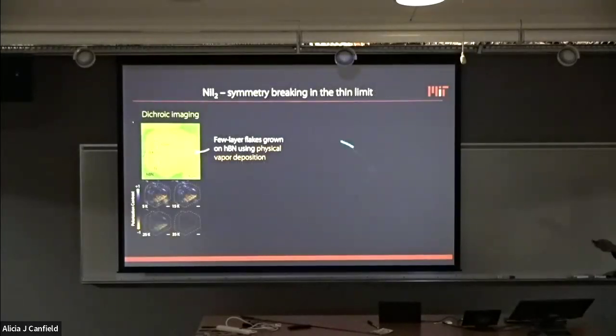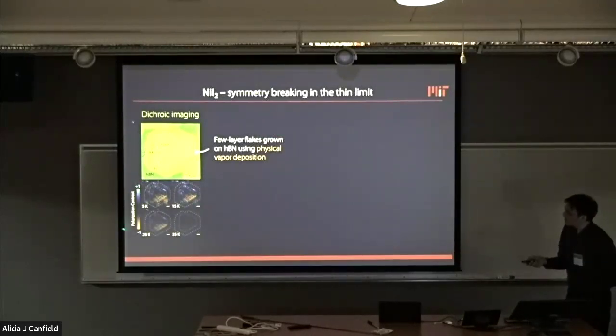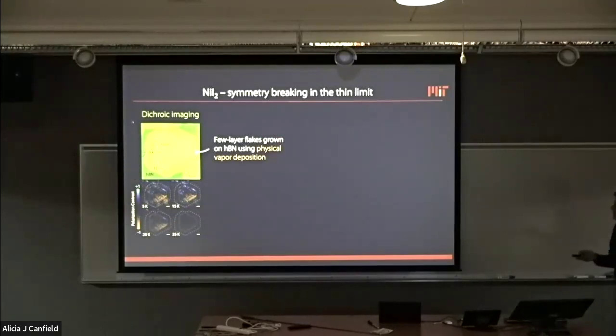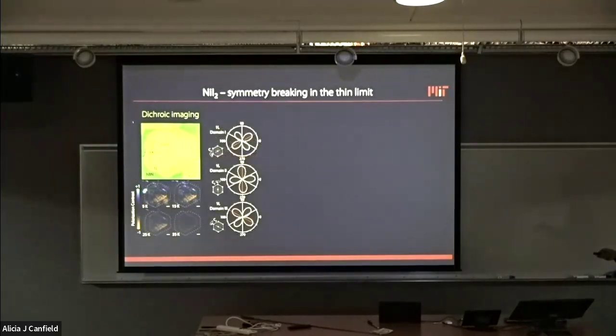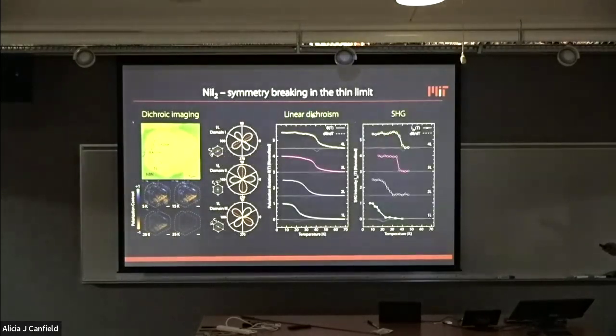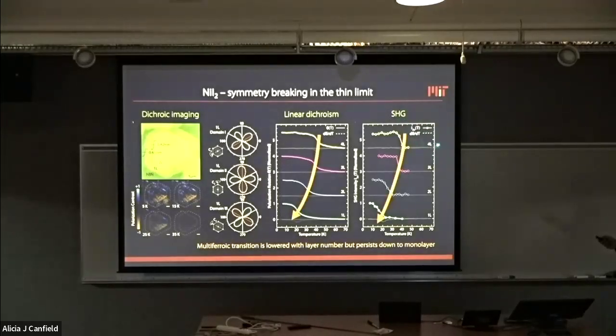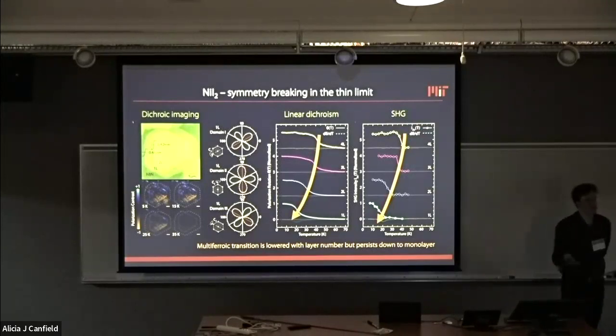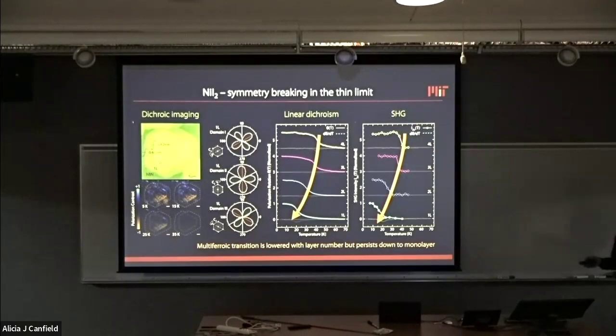So we have a few layer samples. We see that at low temperature, in both bilayer and monolayer, there is a formation of these multiferroic domains. We see this in the cross-polarized imaging. So we see the signatures there already, and we see the different domains. We can track them with the linear dichroism, but most importantly, we can perform the dichroism and the SHG measurements. And we see that going all the way into the ultra thin limits, so now 4-layer, 3-layer, 2-layer, and 1-layer, the transition temperature is reduced, but the multiferroic state is retained all the way to the single unit cell limit, the monolayer limit.